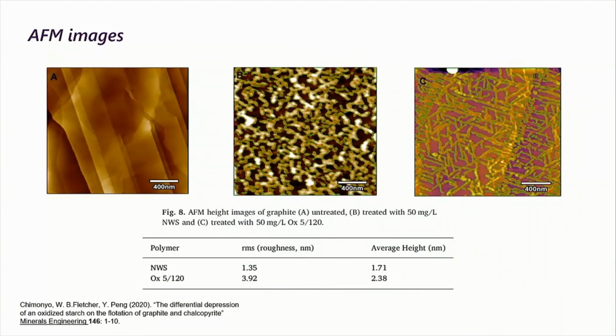Here are AFM images. On your left there is just the native substrate. This is highly ordered pyrolytic graphite, so it might not represent the real situation that well. But anyway, you can see in the middle there you've got the native wheat starch, and on the right there that's the Ox5 120. It's got a far more geometrical and ordered type of adsorption of the polymer chains onto the surface there. Surprisingly though, when you have a look at the roughness and the average height between, say, B and C, the native wheat starch and the oxidized starch, you're getting more for the oxidized starch there.